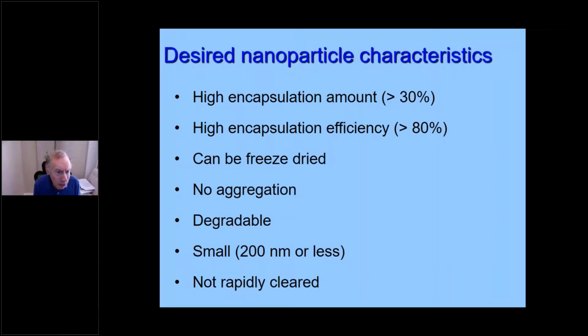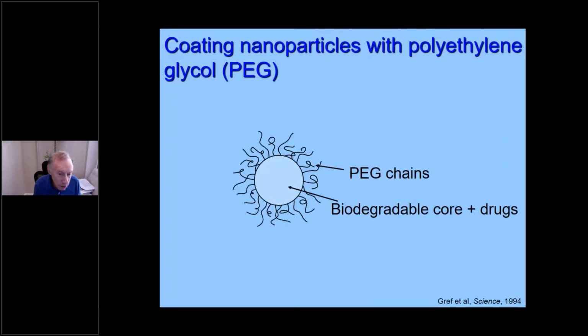We wanted a high encapsulation amount, high efficiency, that they could be freeze dried, not aggregate, be degradable, be small, less than 200 nanometers, so they could get into a cell and not be rapidly cleared. And what we did is shown on the next slide, that we could make coatings with polyethylene glycol, which could actually provide a disguise. And I should point out that there are a number of groups; we collaborated with Vladimir Torchilin, who was one of the groups that did some of the early work on this, but there are others too, who had done work with these in different manifestations, like Bob Davis, Jun Wang, and Dr. Kataoka from Japan. He did micelles.